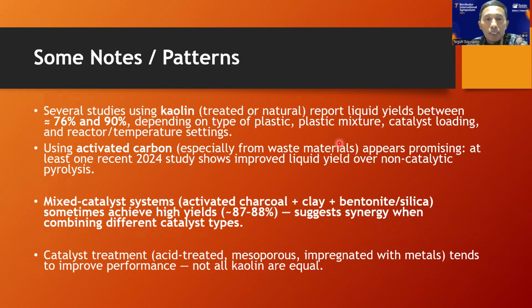Several studies using kaolin report liquid yield between 76 to 90%, depending on the type of plastic mixture, catalyst loading, and reactor temperature setting. We can also understand that pyrolysis has many factors that influence the result. And using activated carbon, especially from waste materials, appears promising; at least one study in 2024 showed improved quality and liquid yield over non-catalytic pyrolysis. And also mixed catalyst systems.